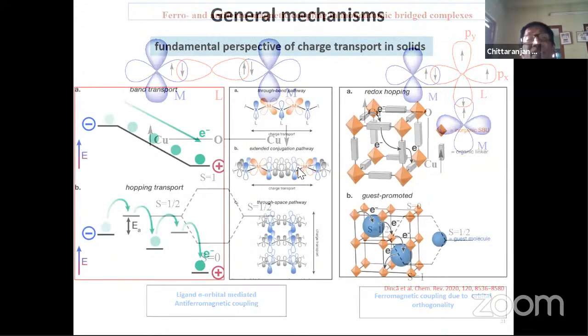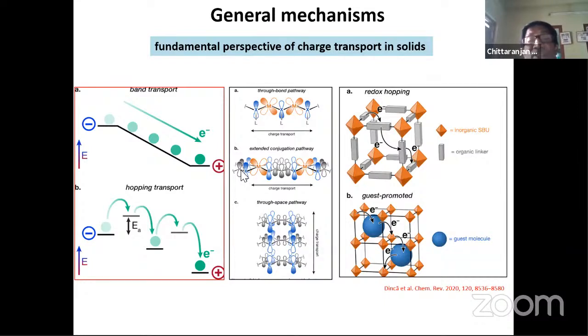And that spin change is being used in the charge transportation process, and the charge transportation through bond and through space. When the metal organic framework, you see, just consider the Prussian blue. In Prussian blue, you know, iron is bridged by cyanide. One iron 2 is bridged by cyanide to another iron 3. Iron 2, cyanide, iron 3 bridging. So one electron may come from iron 2 to iron 3 through the cyanide bridge. Thus, the metal to metal charge transportation is responsible for its long range electron transfer process.